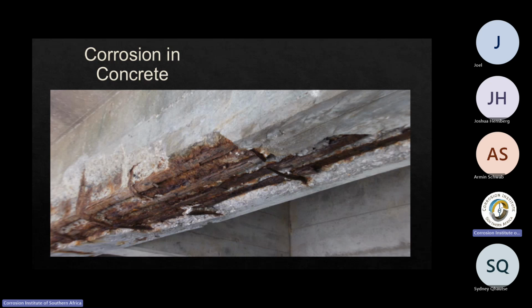What about concrete? What do we mix concrete with? Potash. So we've got ash, we've got soil. Again, we've got all our minerals that's in the soil, and we add water into it. And depending how clean the water is, it might have high chloride levels or low chloride levels. And most of the time, they take the hose pipe and they chuck it in. They don't test the water before they do it. Now you take your concrete and you put some structural steel to strengthen it. What have you got? You actually have a perfect corrosion cell that's set up.